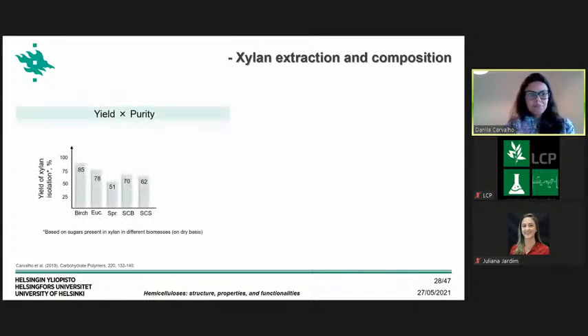In terms of purity, we could see that the purity of the sample was quite, in terms of, this was more about the yield actually, and the yield was quite reasonable, except for the spruce. But the spruce, since the mannan is the main hemicellulose present, the mannan was also co-extracted with the xylan. Then we spent several steps of purification in order to get the purity that we wanted, but this also compromised the yield because in every step of purification, part of the xylan was removed from the biomass that we were preparing.